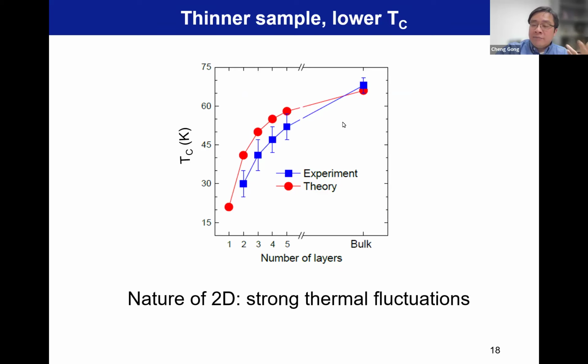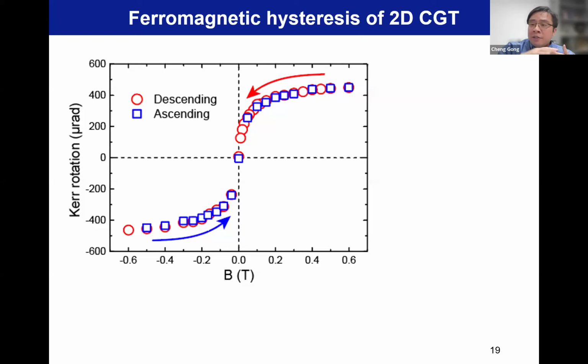This clearly shows a dimensionality effect. When the sample becomes thinner, the TC is reduced compared with its 3D counterpart. So this directly reveals the strong thermal fluctuation in the system. The renormalized spin wave calculation confirms this trend. So this is the temperature dependent data. And the other evidence we usually need to prove ferromagnetism is the magnetic hysteresis loop.